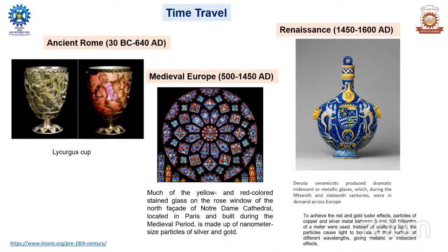It's an image of King Lycurgus, but what happened is that it puzzled a lot of people. It was not solved until some 1950s, when the glass material was scrutinized, and it was seen in the broken fragments that, completely unintentionally, the artisans who made this impregnated the glass with small particles of silver and gold, as small as 50 nanometers.